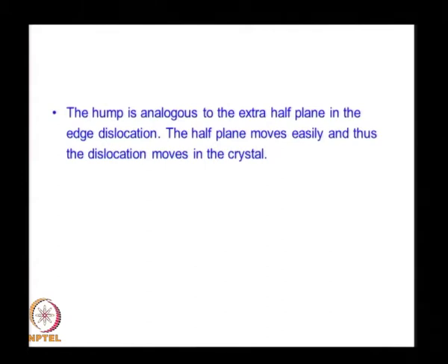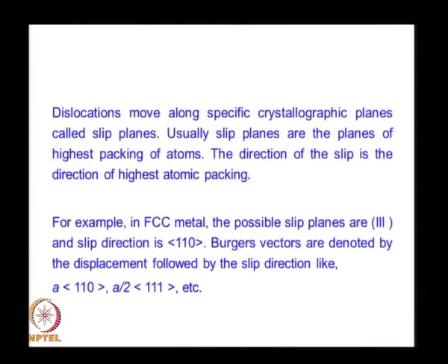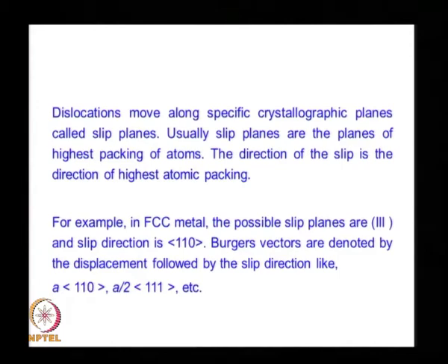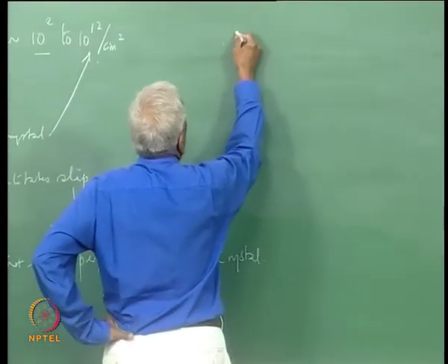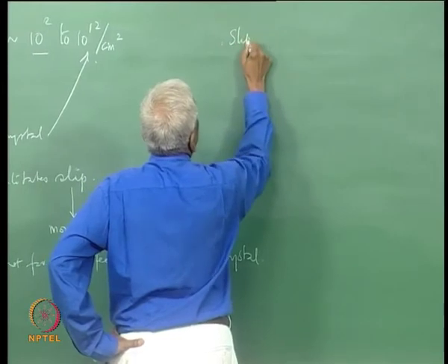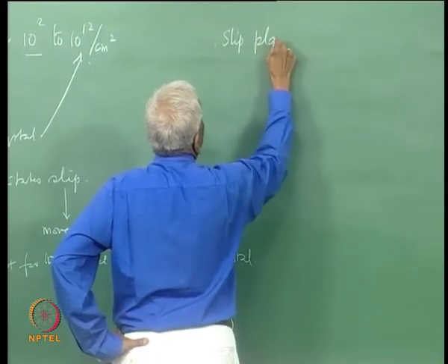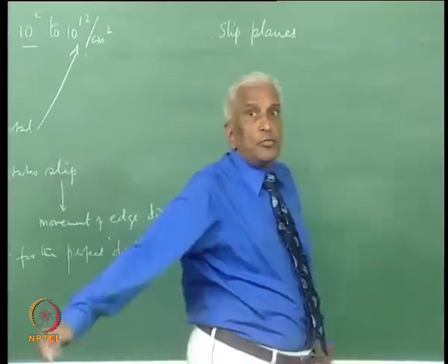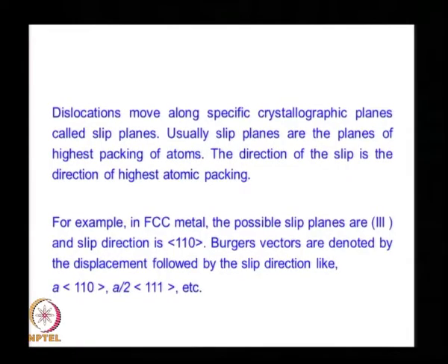The hump is the analog of the extra half plane in the edge dislocation. So, this half plane moves easily, and thus the dislocation moves in the crystal. They move along specific crystallographic planes. These crystallographic planes along which they move are known as the slip planes. So, the movement is not along any arbitrary direction.